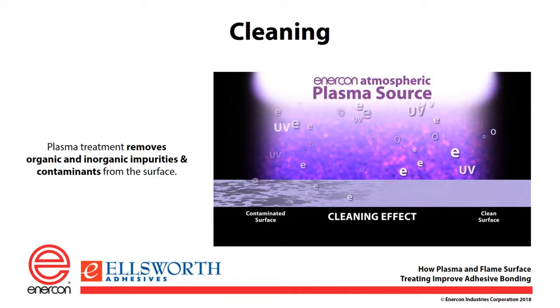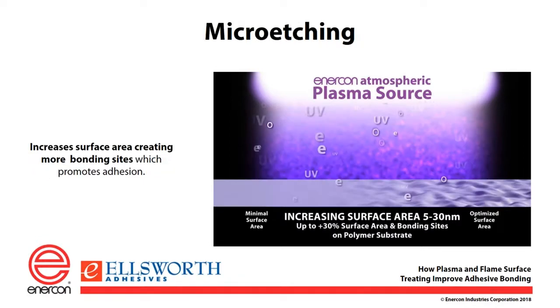This is a little slide that kind of goes through what happens when you treat a surface. This is the cleaning step. So basically, you're going to do three things. First is cleaning. So you have contamination on the surface, and the plasma or the flame will clean that off, whether it's organic, and many inorganic impurities can be removed. This is done by first taking all the static off the surface, so anything being held on by static gets removed, and then it will clean the other impurities off of there as well. Not all impurities, but most.